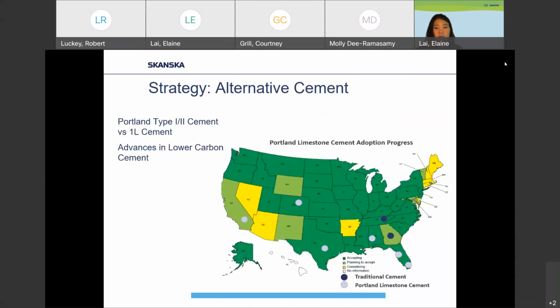Another strategy here is alternatives to cement. So a very common available cement type is what they call Portland limestone cement. It's an alternative to the traditional type 1-2 cement. And we're seeing an increasing availability of this type 1L cement across the US. Typically, you can substitute out a portion of the cement with limestone. So type 1L is substituting cement with anywhere in the range of 5 to 15% limestone.